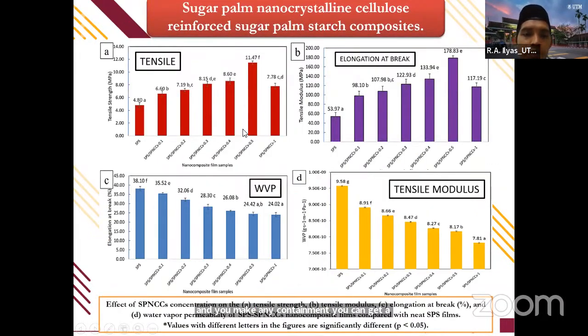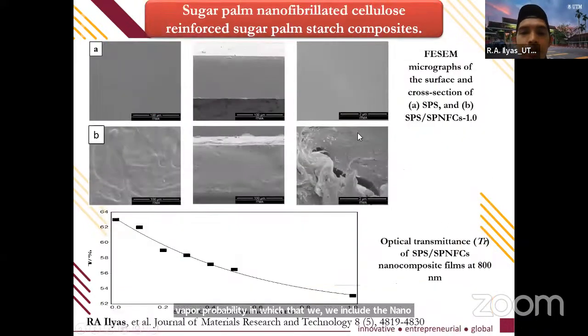We can see that when we reinforce with nanocrystalline cellulose, we add only 0.5, and the tensile strength is increased up to 11.47 megapascal, compared to the raw starch, which is 4.8 megapascal. So it increases up to double. And besides that, we can also see that when we include the nanocellulose, the water vapor permeability is decreasing, which means that it improves the water resistance.